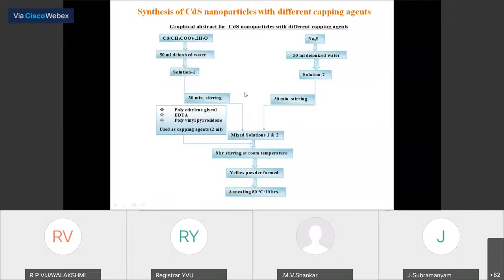Then we have the two solutions. We combine them in the required stoichiometry. We fix the molarity, and by fixing the molarity we prepare the two solutions. After preparing the two solutions, we stir them for 30 minutes. Then we add three capping agents: polyethylene glycol, EDTA, and polyvinyl pyrrolidone. These are the three capping agents we have used to synthesize the cadmium sulfide nanoparticles.